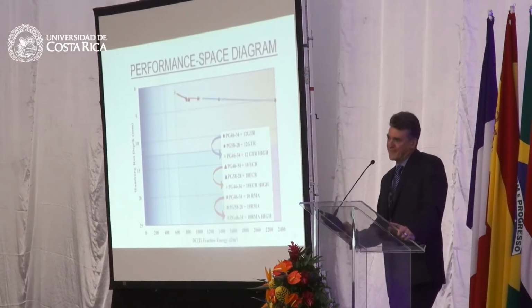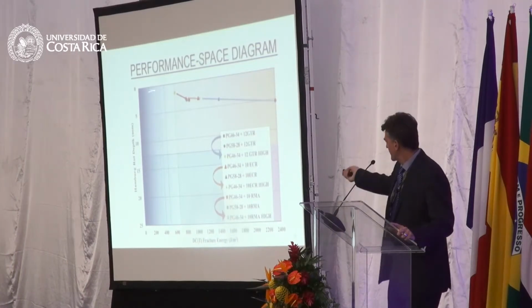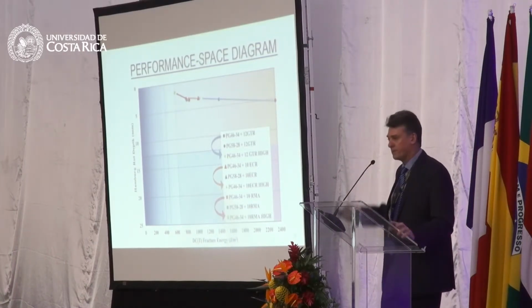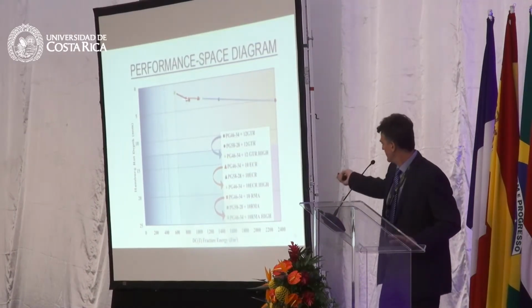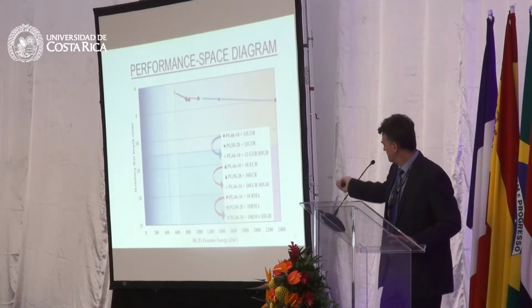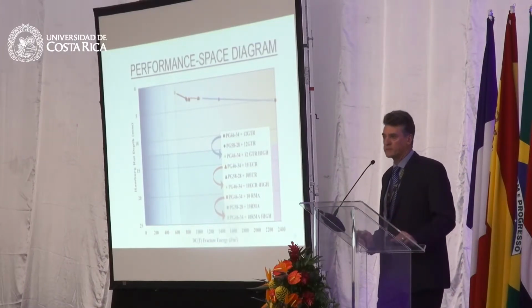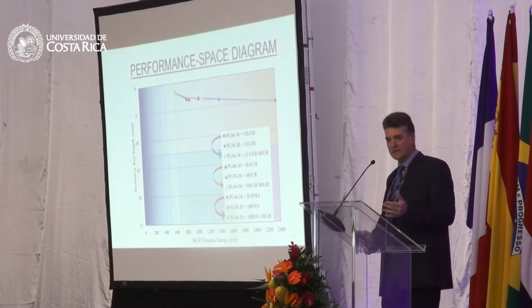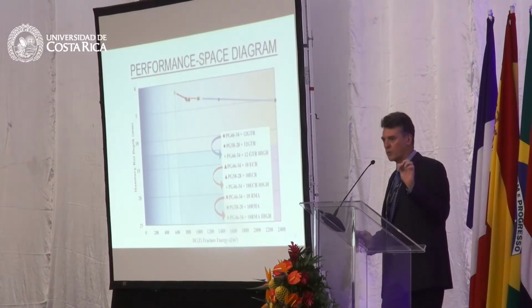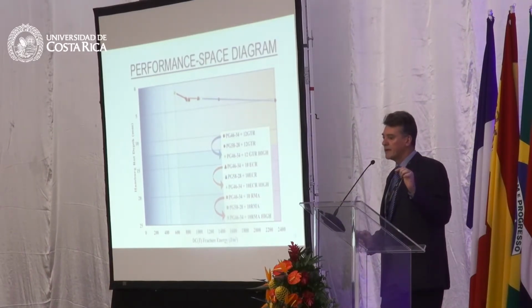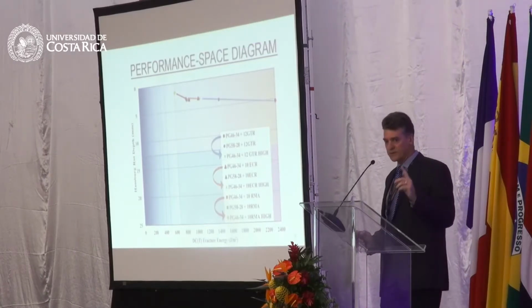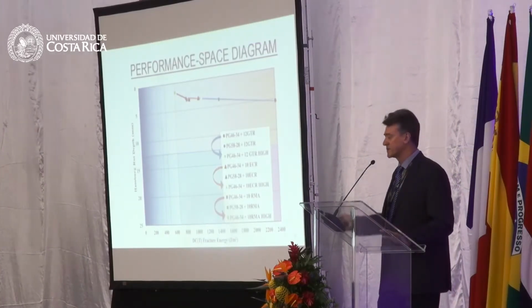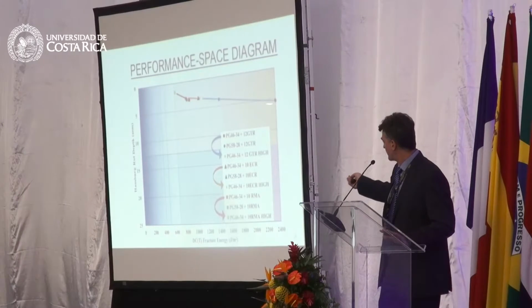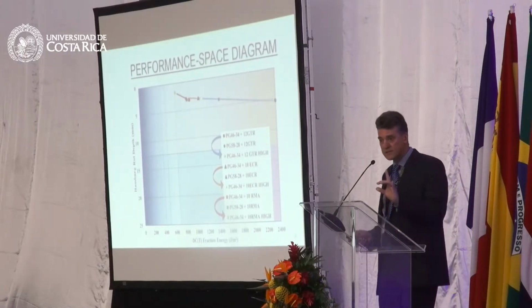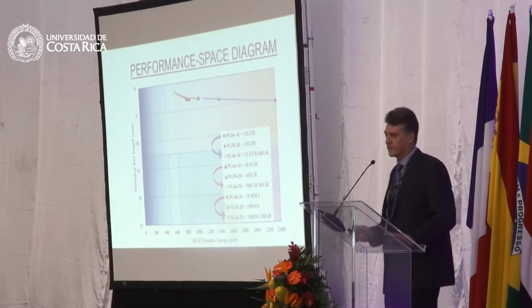What's interesting in this data set is that the slope of this line is fairly flat compared to the other trends that I've seen. We've had more diagonal lines on the performance space diagram. I think that has something to do with the role of the swelled ground tire rubber. And what it suggests to me is that there's an opportunity on these mixtures to use a very soft base binder and still resist rutting fairly well.